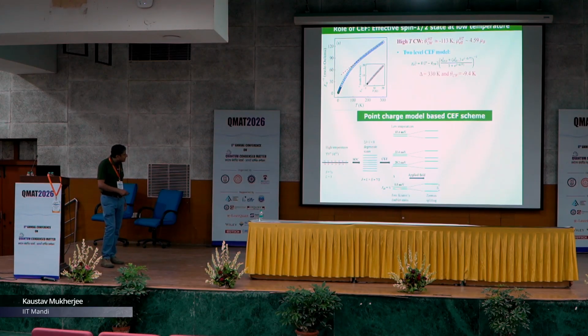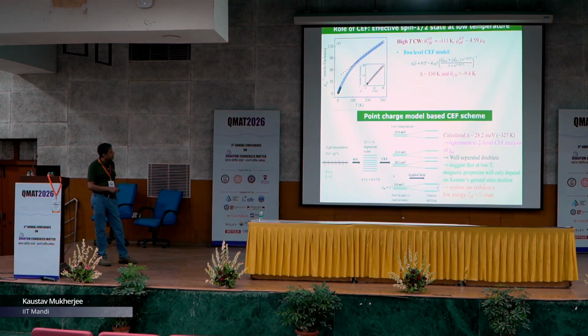And under crystal electric field we get 4 Kramers doublets of different energies, and what we found is that the value of delta obtained from this point charge based calculation was around 28.2 meV, which is approximately 327 Kelvin, and it is in good agreement with the value obtained from the 2-level crystal field analysis of the chi-DC data.